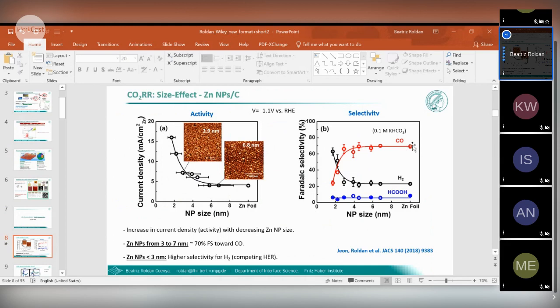If you look at the selectivity, we are making CO, that is the product that we want to make with zinc. But if you go to particle sizes below 3 nanometers, you see a decrease in the CO selectivity, and you see the increase in the hydrogen evolution reaction. This is, in this case, our parasitic reaction.